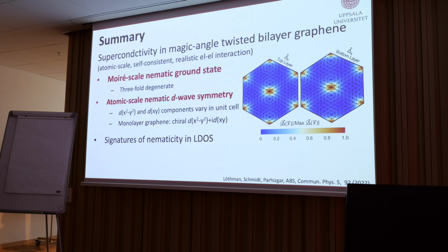But also, if you look at the atomic scale, I have a variation between the two d-wave solutions, which doesn't happen in graphene. And there's also some signature of the nematicity in the density of states. So we did this a couple of years ago, and that was interesting. But we always wondered how much we had assumed, how it fits with experiments, and how it compares.